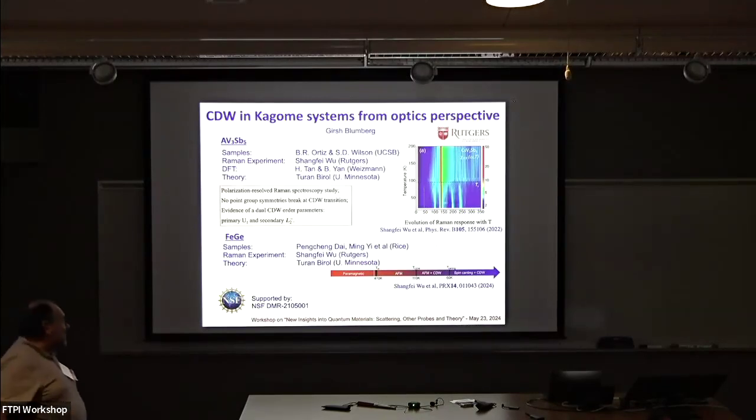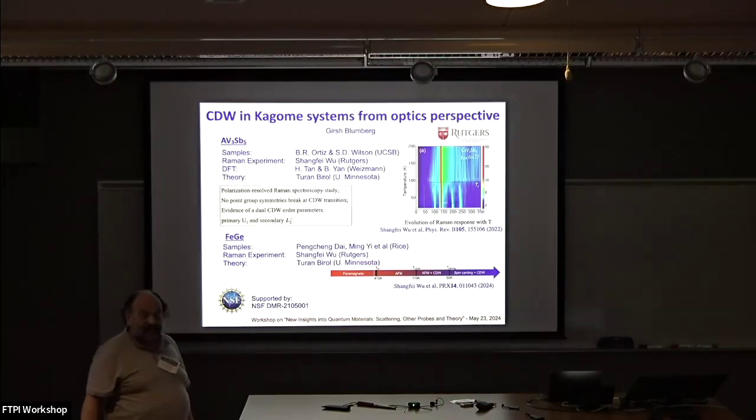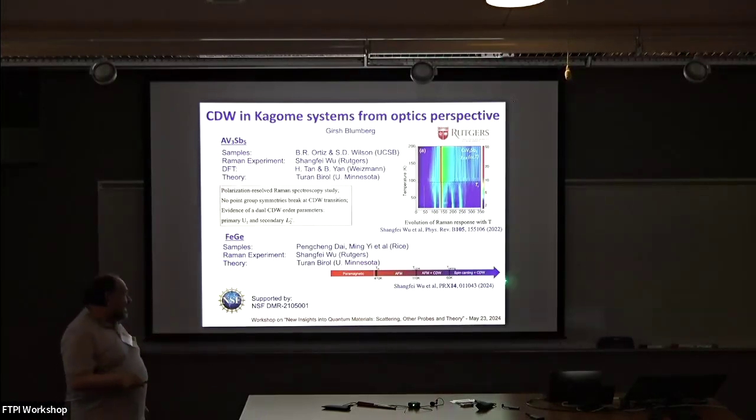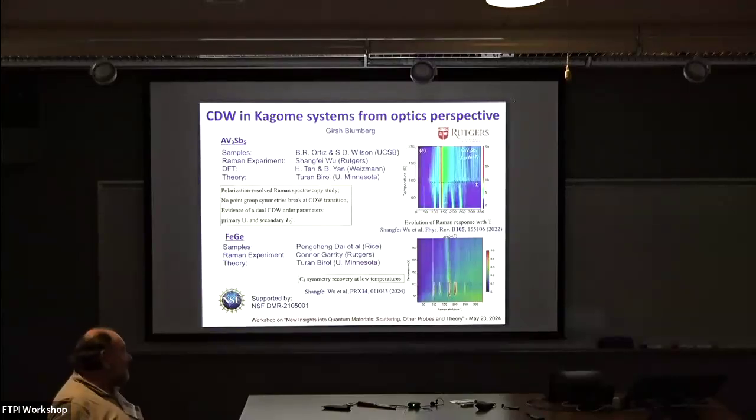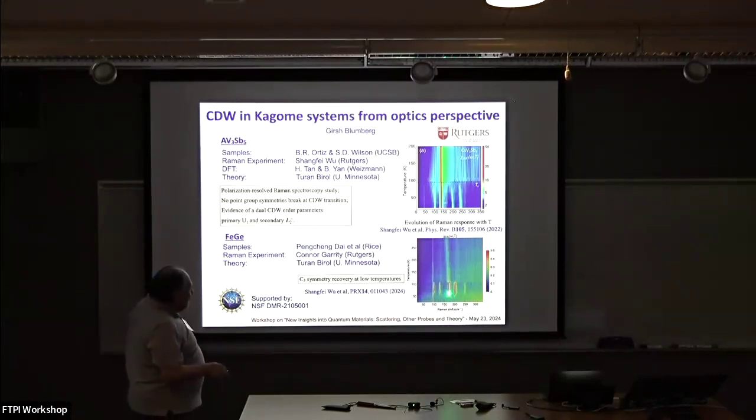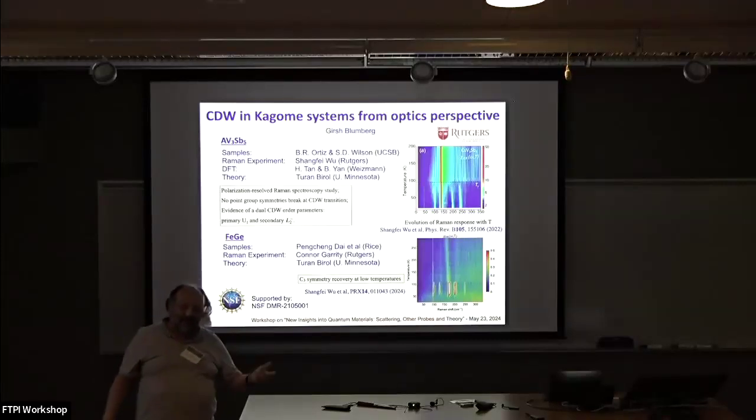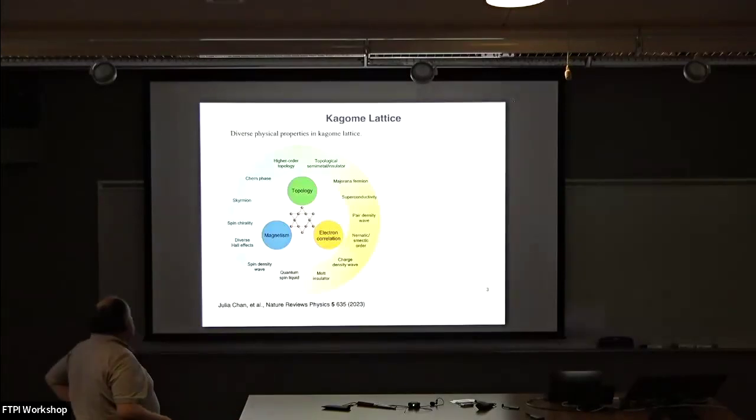And then there is another transition, the so-called spin-canting transition. The biggest surprise here was that in this low temperature phase, the broken symmetry recovers. At high temperature you break the symmetry, and then, seemingly violating laws of thermodynamics, you would think initially, it recovers. You can clearly see from the Raman data that this is the CDW phase. You see new modes appearing here, and I can tell you a lot about those things. But in the low temperature phase, the situation recovers back to one single allowed mode, and we have some explanation why.